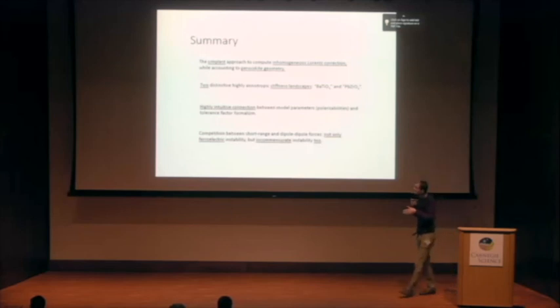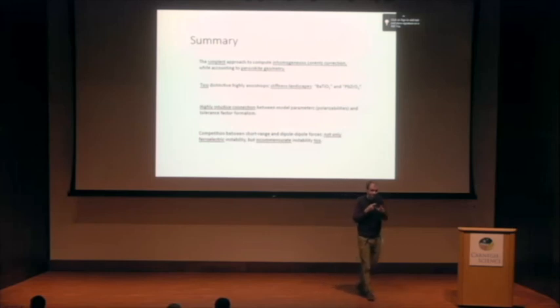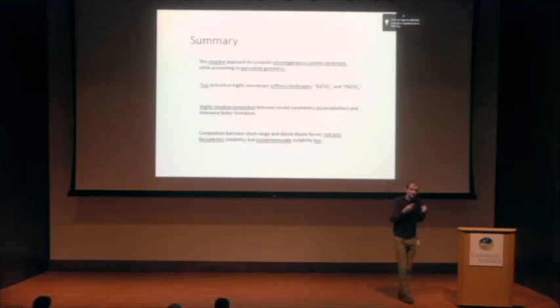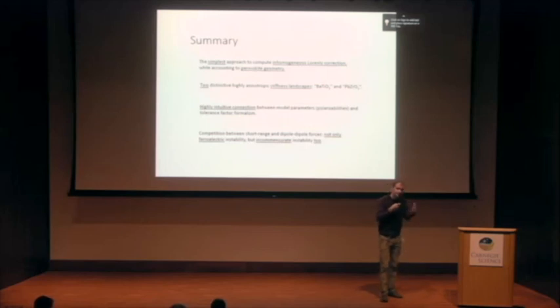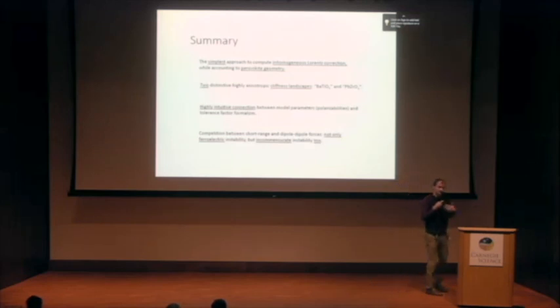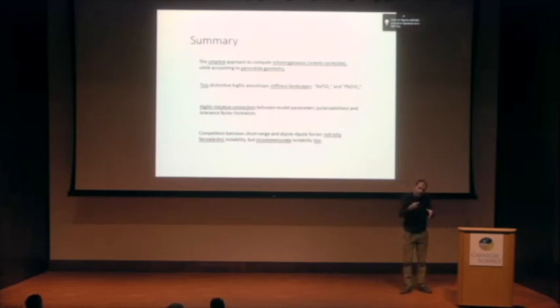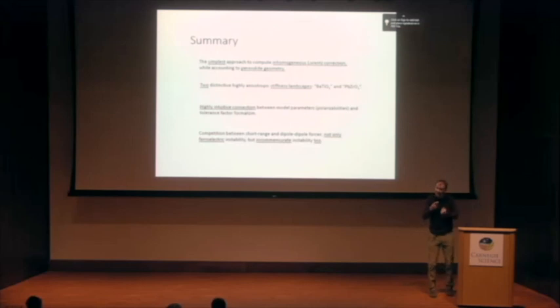And then the competition between restoring short-range forces and destabilizing Coulomb forces is not only responsible for making ferroelectric instability, it can make also incommensurate instability or, for example, antiferroelectric instability if these incommensurate phases do lock in. So basically the explanation can be in principle as simple as that. And let's say it is intuitive that much that I tend to trust this view. It is very simple, but I think it might make sense.